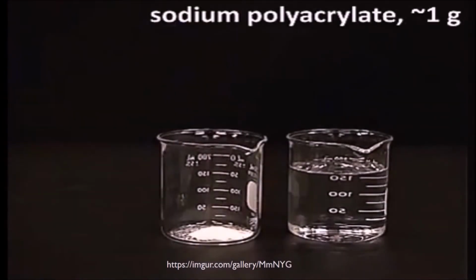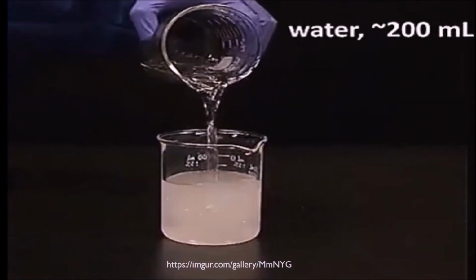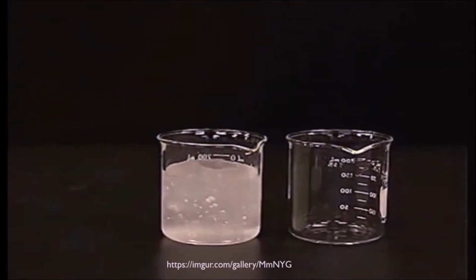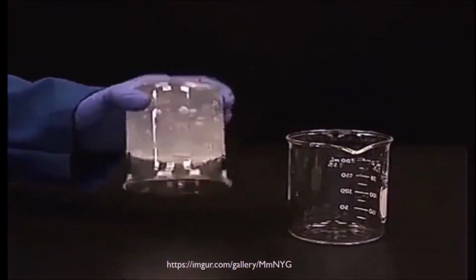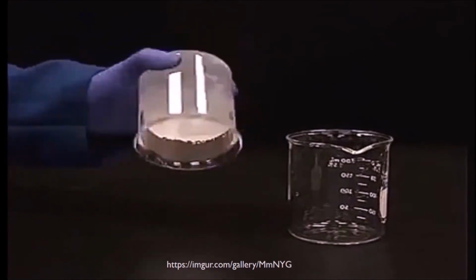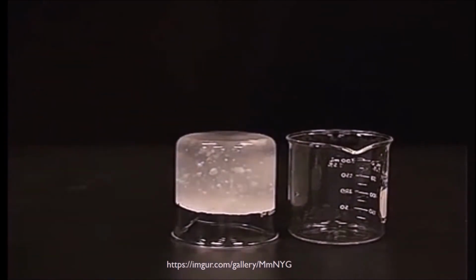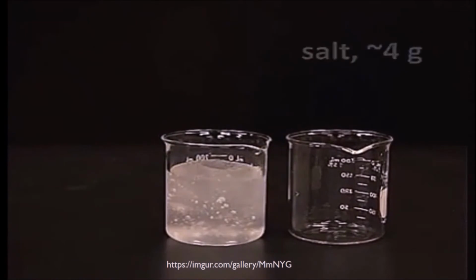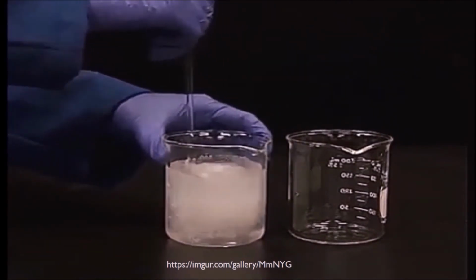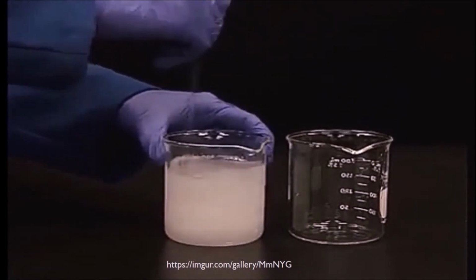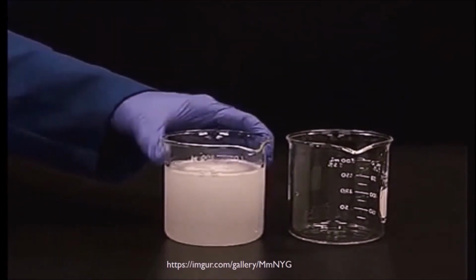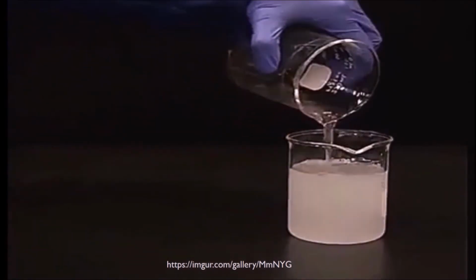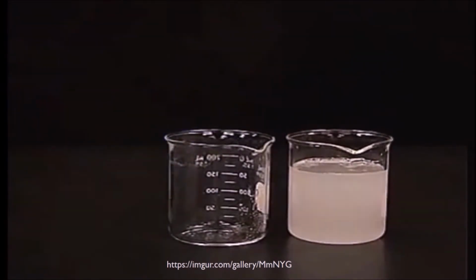In this video, 1 gram of sodium polyacrylate is mixed with 200 ml of water, and this results in the formation of a highly viscous solution, as shown in the video clip. But when a few grams of salt is added to this solution, the viscosity falls and the solution behaves as a normal solution. Now, can you guess why this happens? Well, I could give you a hint. It is related to the basic difference between a neutral polymer and a polyelectrolyte.